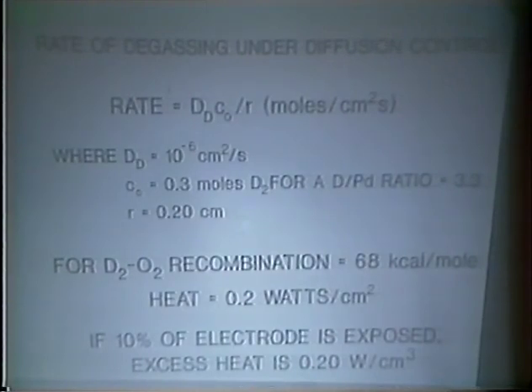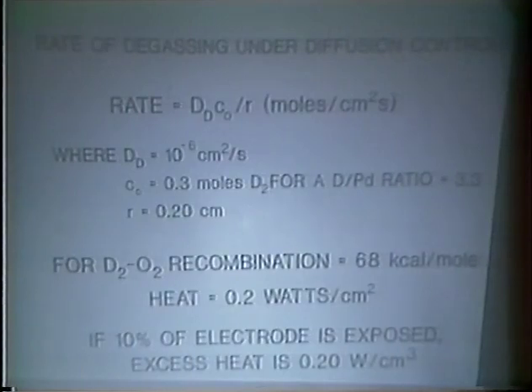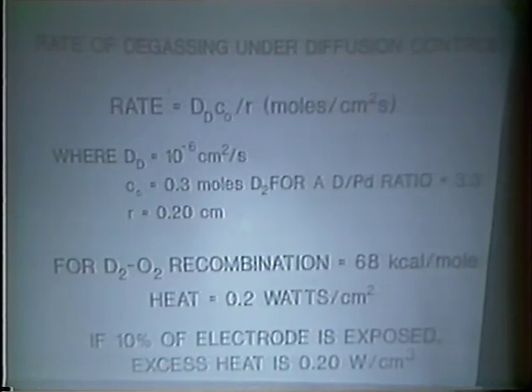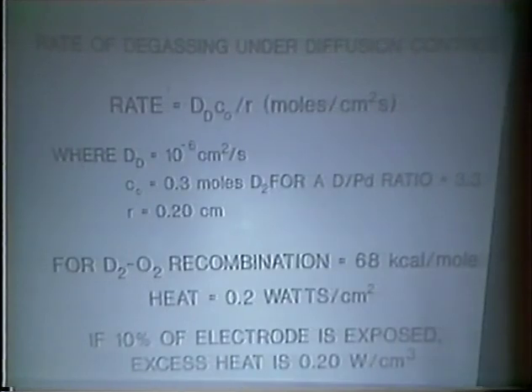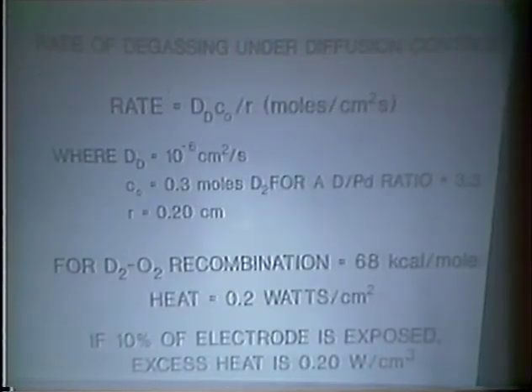And depending upon the surface films, we assume we get results which go down to 0 or negligible totally. And with the assumption of a 1 micron film of water, the heat then comes to 0.2 watts per cc. It's not watts per square centimeter, watts per cc.